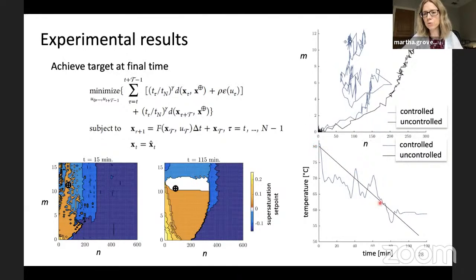So if we just apply a linear cooling temperature, then we get over here where we have a lot of crystals, but maybe we want to have larger crystals. So in that case, we apply our optimal policy, and it drives us by having the temperature go up and down according to these colorful policies, and to achieve our desired state. And here we have a time varying policy, unlike the constant control policy. So at 15 minutes, the optimal policy is different than at 115 minutes towards the end of the batch. But here the blues are associated with undersaturation and dissolving, whereas the orange and the yellow are associated with a positive supersaturation to drive nucleation and growth.